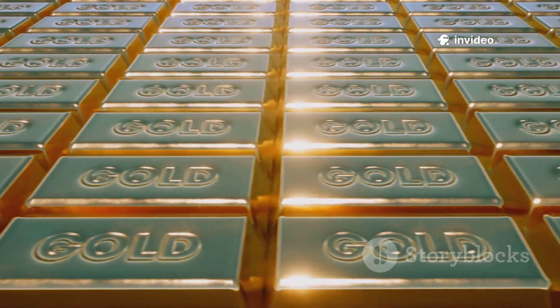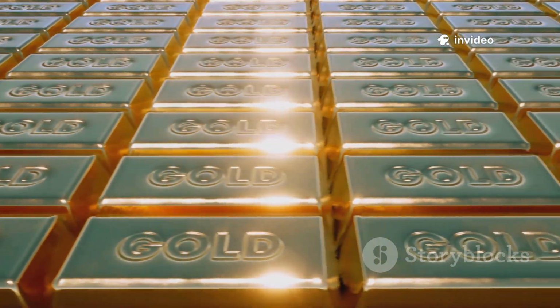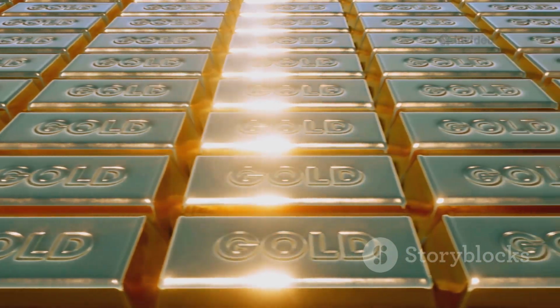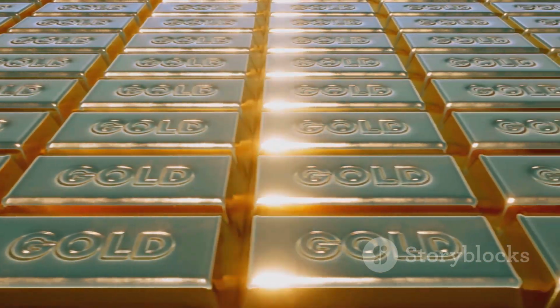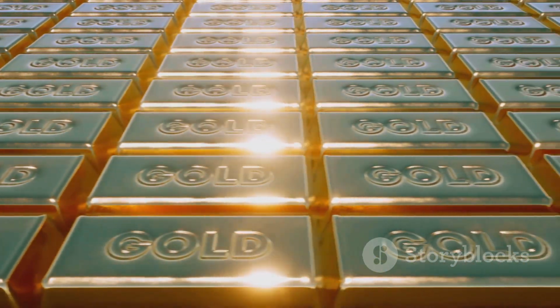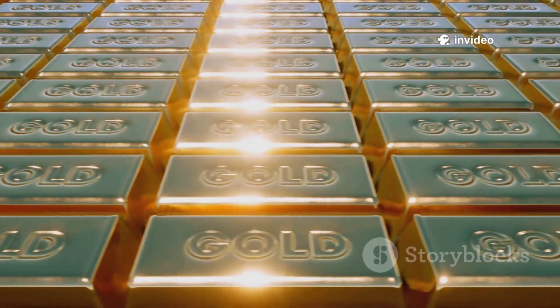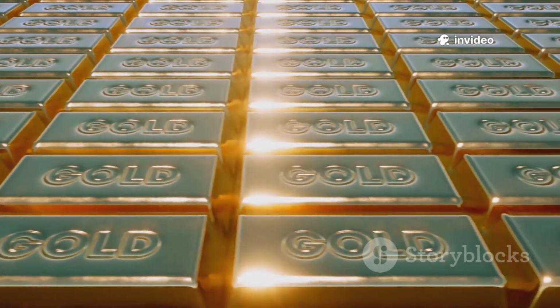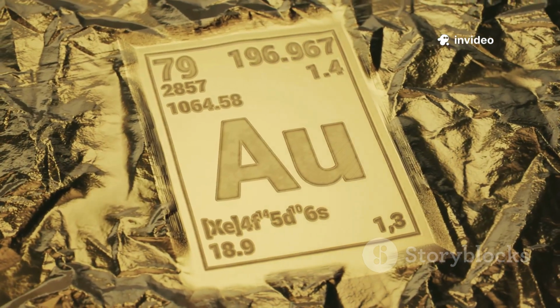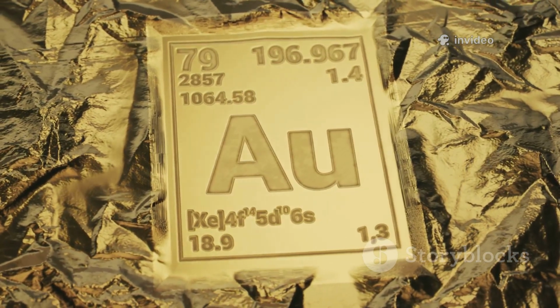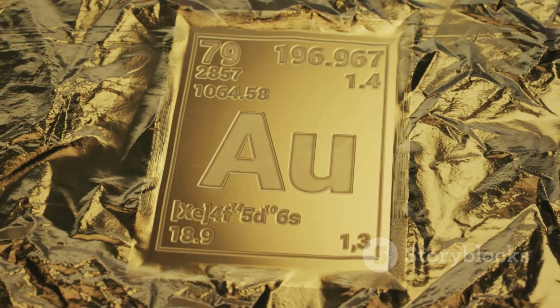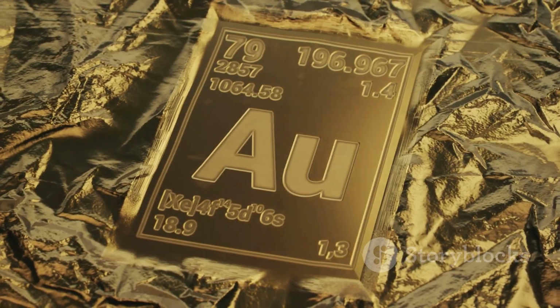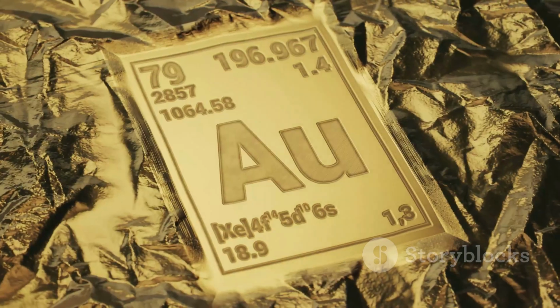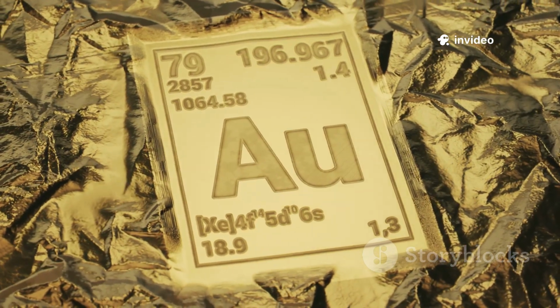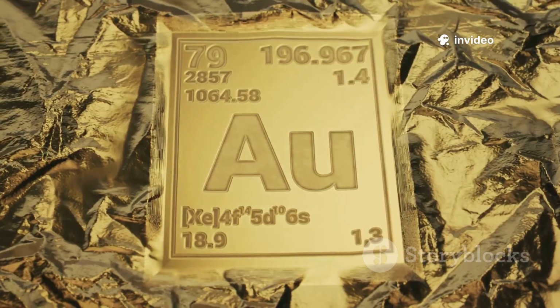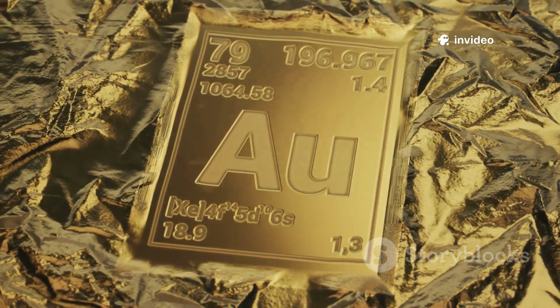This is very pure, but for the world's most expensive bars, we need to go one step further to get from good to perfect. To reach that coveted 99.99% purity, a second process is often used, the Wohlwill process. This is an electrolytic method similar to the electrowinning we saw earlier but much more precise. The 99.5% pure gold from the Miller process is cast into anodes and placed in a bath of chloroauric acid. A small, thin sheet of ultra-pure gold is used as the cathode.